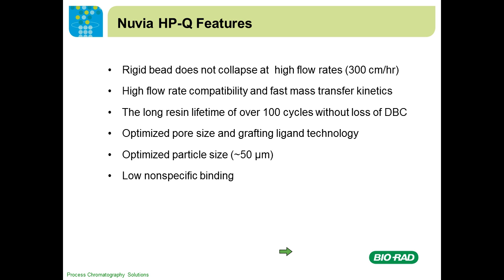The feature of Nuvia HPQ, as I mentioned, is that these are very rigid beads, which allow you to run at high flow rate, together with the large pore structure, so you are able to have fast mass transfer. Combined together, you are able to achieve high binding capacity and high flow rate, and then improve your productivity.